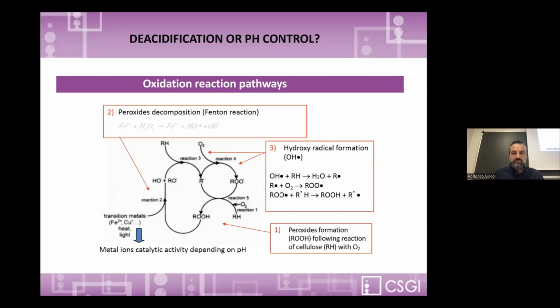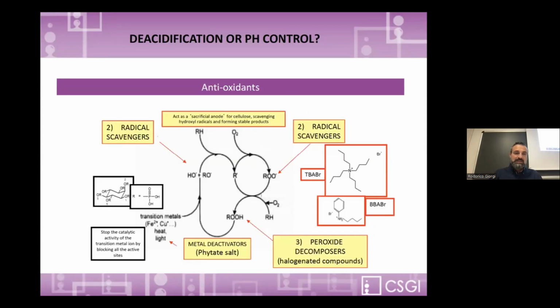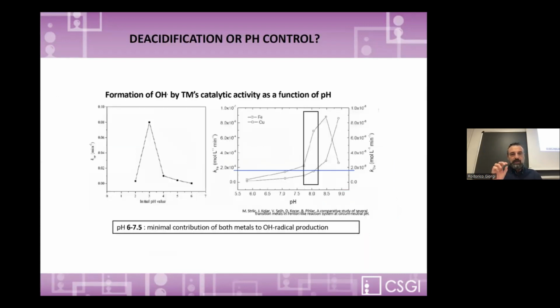And for this purpose, as I already told you, antioxidants are applied. Antioxidant in the sense that we apply something that can inhibit this process that leads to oxidation. And so we have the possible use of real antioxidants, like, for example, radical scavengers or peroxide decomposers, which are halogenated compounds or ammonium salts. And the well-known phytate, that is a metal deactivator, a way to remove free iron ions, which is the starting point of the process. But the catalytic activity of metals strictly depends on pH.